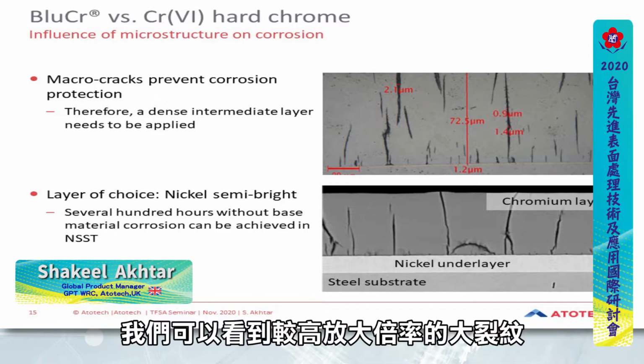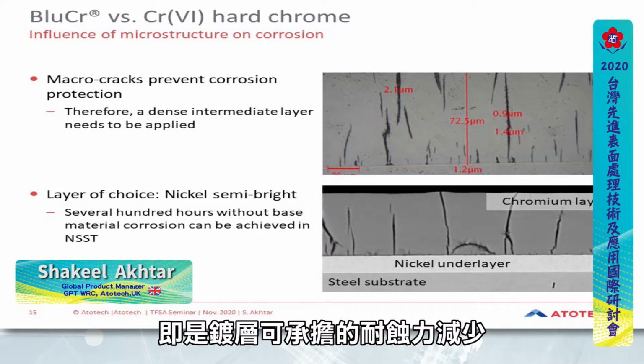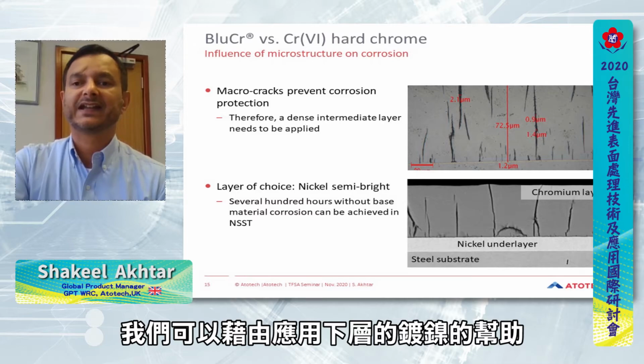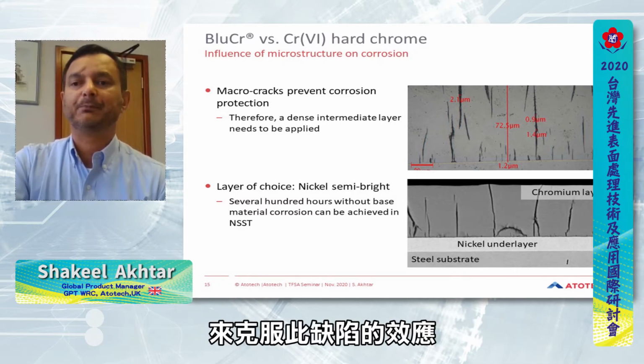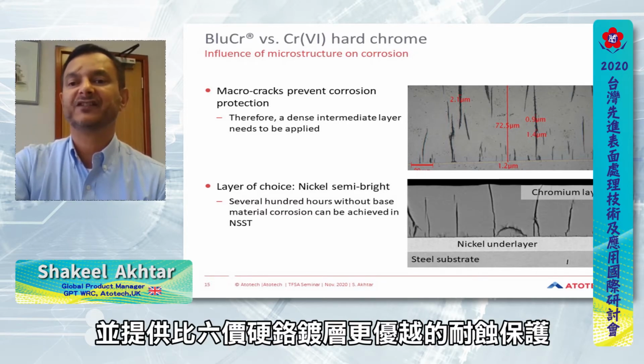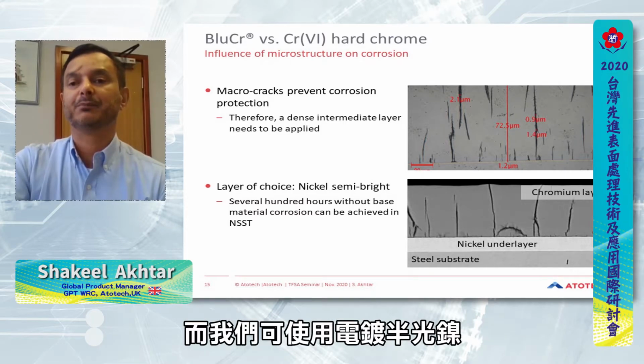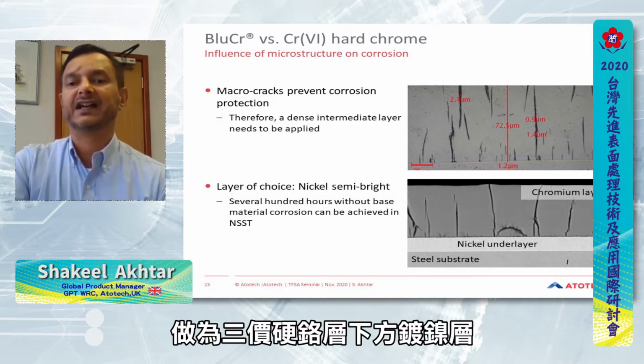In slide 15, we can see the macro cracks at a higher magnification. A negative consequence of these macro cracks is that the corrosion protection afforded by the deposit is reduced. However, we can counter this effect by the application of a nickel underlayer, which helps to overcome this deficiency and provide superior corrosion protection compared to hexavalent deposits, as we will see in the following slides. Semi-bright electrolytic nickel can be used as the underlayer.